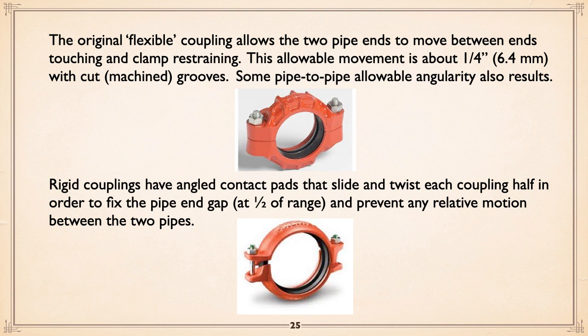Now, rigid couplings, for a long time, this was a plus and a minus at the same time. If you've got a lot of couplings, you ended up with too much flexibility because that 1/4 inch can add up. So rigid couplings were developed. And basically, if you look at where the bolt is on the left there, you can see that the pad where the two coupling halves meet is at an angle. So what actually happens is you tighten the thing, it twists each coupling a little bit up against the groove, so as to block it at about half the range. In other words, where it's typically 1/4 inch, it'll be frozen at about 1/8 of an inch.